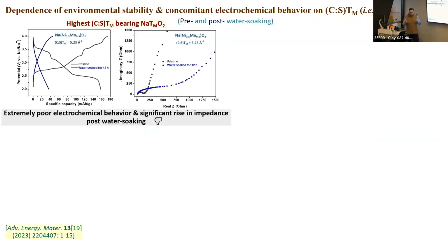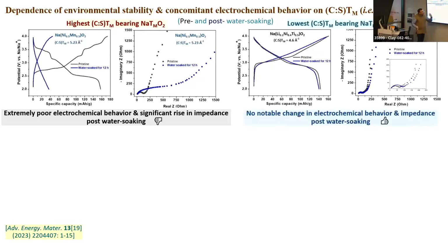Now coming to the electrochemical behavior after soaking in water, the one bearing high charge to size ratio shows a near complete degradation. I mean, it does not cycle after it's soaked in water. As simple as that. No need to elaborate further. And the impedance is very high after soaking in water. But the one with the lowest charge to size ratio hardly shows any difference in the electrochemical behavior before and after water. And neither has the impedance increased.